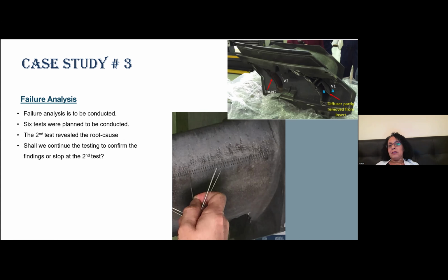When I looked at it, we usually plan what types of tests to do. We were working in labs similar to what you have at the university. We would do macrography, where we look at the macrostructure and imaging from outside. We would do metallography, where we look at the microstructure, cut samples, and see what happened to the material. We would do XRD, for example, on some powder that was collected from there. We could also do XRF on the samples, XPS, SEM, and EDS. So there are lots of tests that you could do.